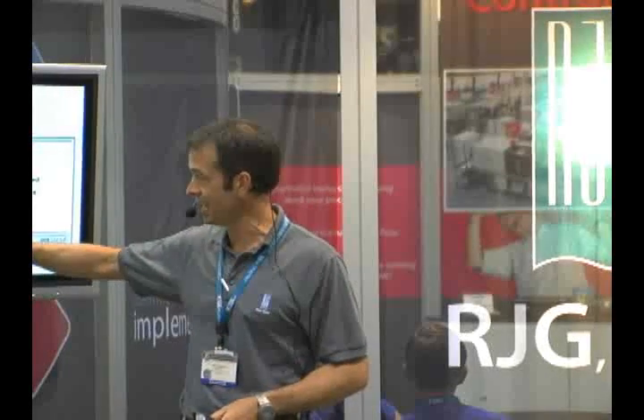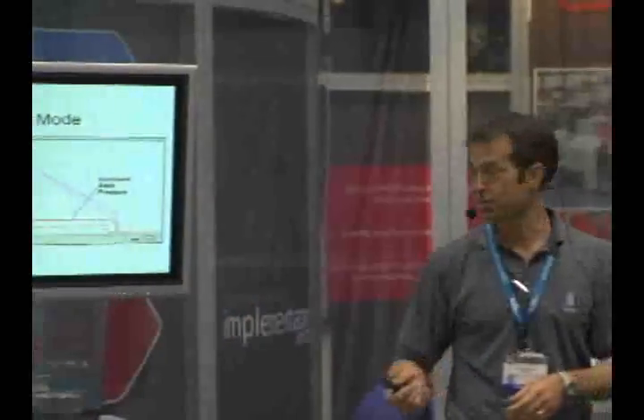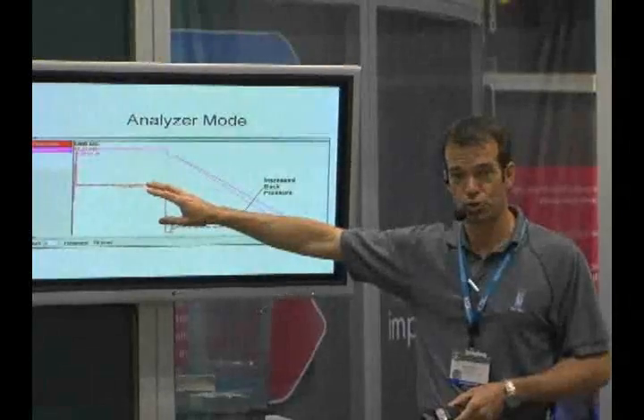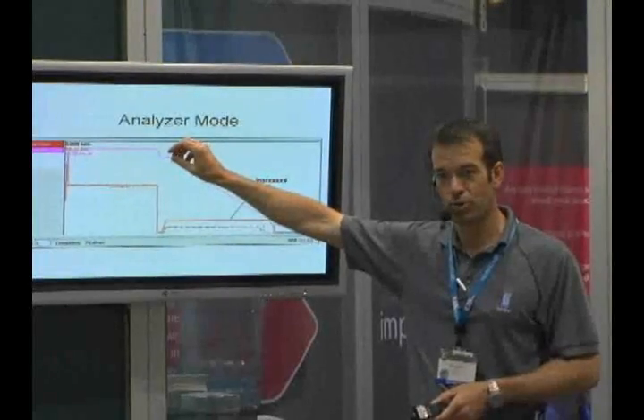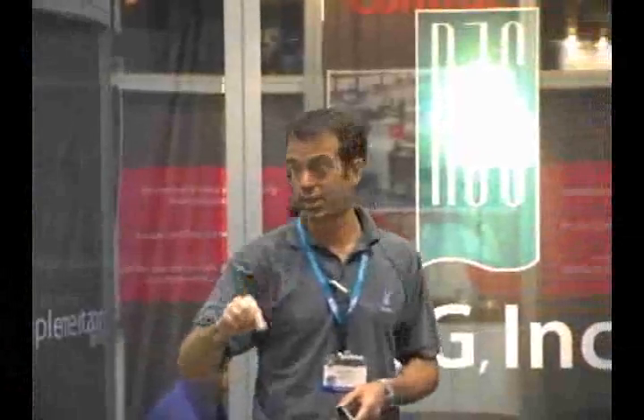Keep in mind, when we went through the validation protocol, we completed the OQ and we've got our successful production qualification done. This data — the dashed line information — was saved as that reference data. It is plastic pressure in front of the screw, it's volumetric flow, information that's critical to plastic property characteristics. I've saved that, and they become the baseline of my measure of whether I'm running to my validated setup.